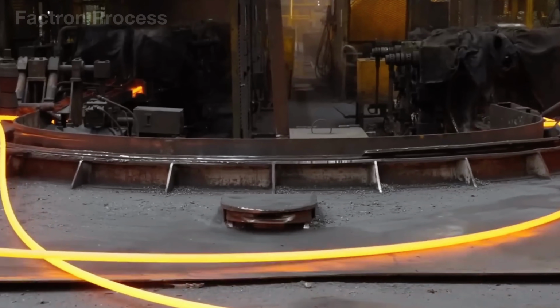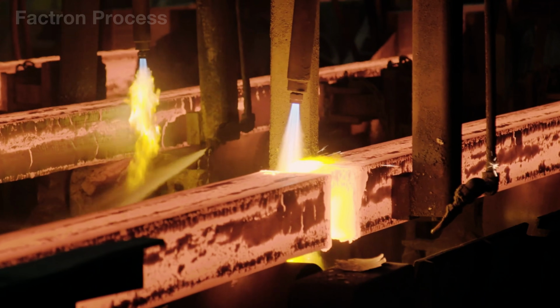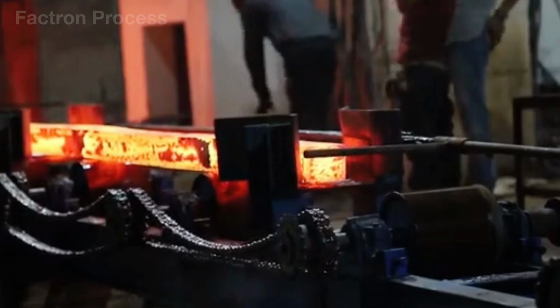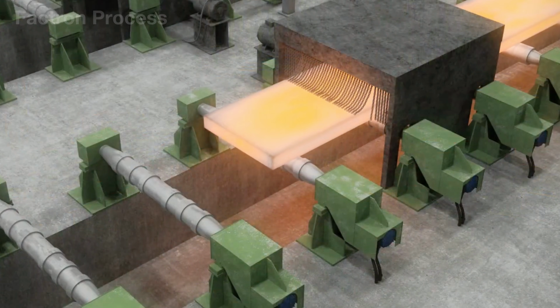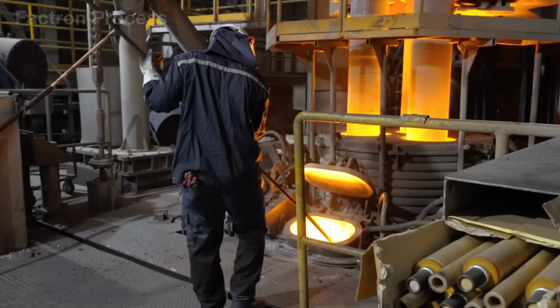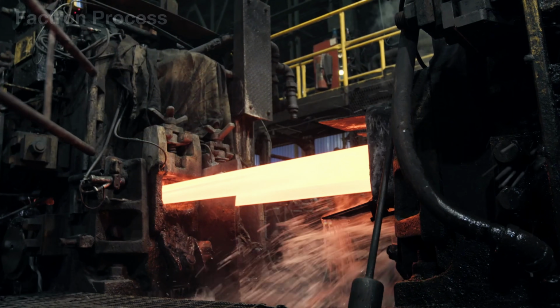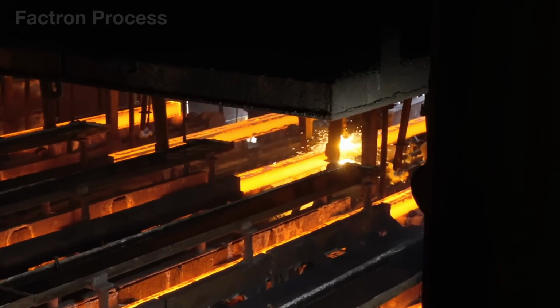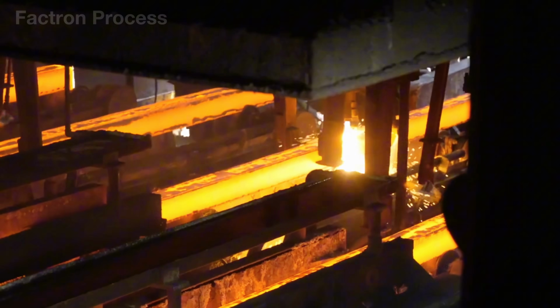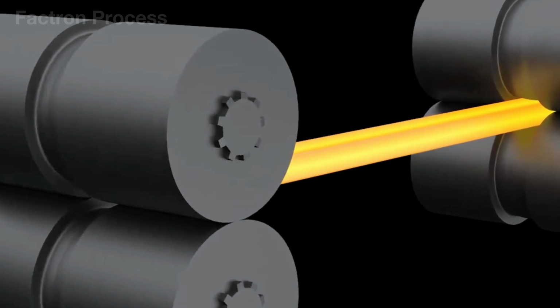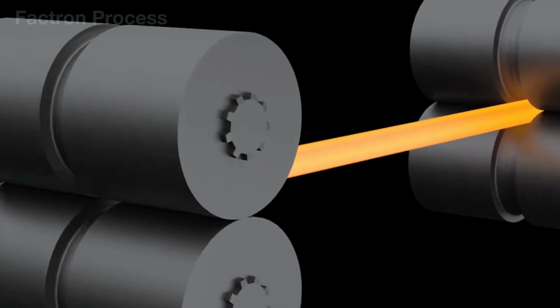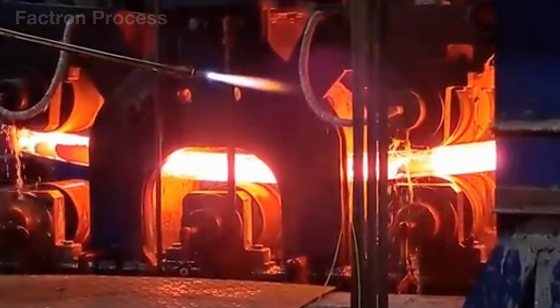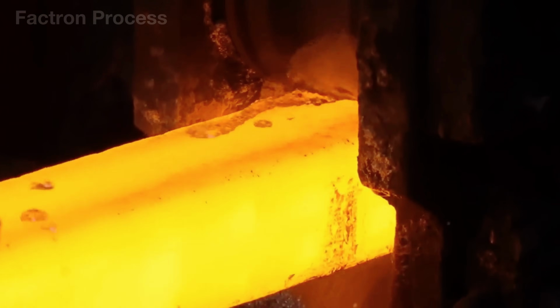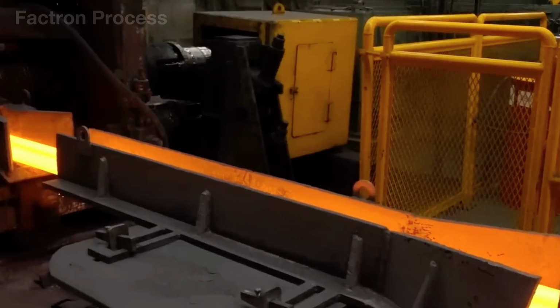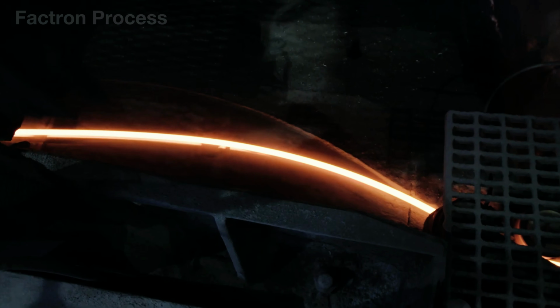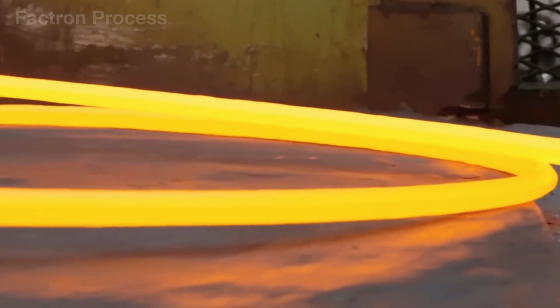Once the solid steel billets have been cast into precise square sections, they are immediately fed into a walking beam furnace and heated uniformly to 2,190 degrees Fahrenheit. As soon as they leave the furnace, the billets pass through a descaling station, where ultra-high pressure water jets reaching 240 bar blast away the entire layer of surface scale. The glowing steel then enters a continuous series of roughing and finishing mills. Here, dozens of massive cast steel rollers repeatedly compress and stretch the red-hot material at speeds of up to 25 meters per second. With every pass through the rollers, the steel becomes thinner and longer.